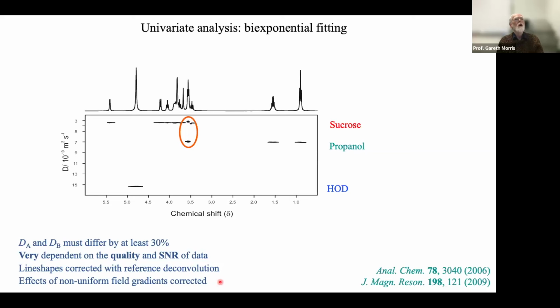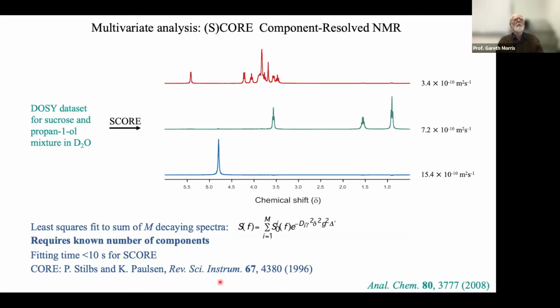Okay, so pitfalls of univariate analysis. Suppose we know that we have only two, or in this case, three species present. We could try to do some sort of statistical fitting and say, well, if we know that there really are only three species there, and we know that we have good exponential decays, in other words, we've corrected for the limitations of our field gradient coil, then we can try to find out what the minimum error is if we fit our experimental data by three arbitrary spectra with three arbitrary diffusion coefficients.